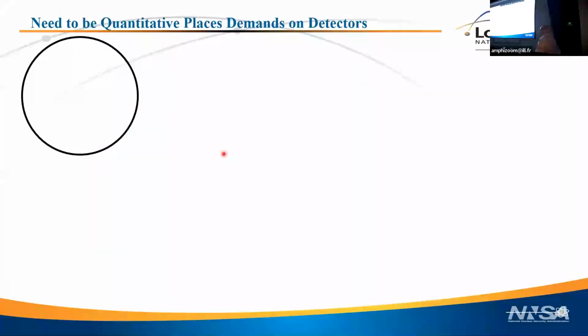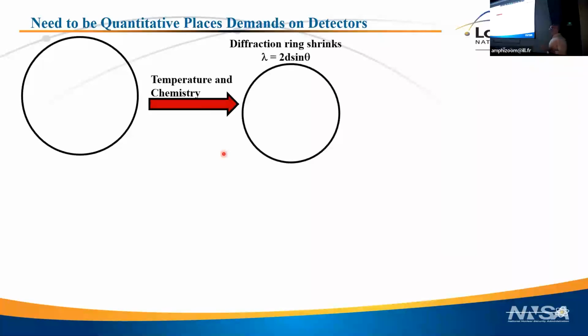So just an example, how do we deconvolute the lattice spacing, for instance, all the microstructural effects on lattice parameter? Well, if we look at just a schematic of a Debye-Scherrer cone, that's supposed to be a circle, right? If we have a stress-free powder or a stress-free sample, then a Debye-Scherrer cone will be a nice circle. If we change temperature, for instance, temperature is a scalar, and maybe I should say this should focus on cubic materials where you have just a single thermal expansion. It's a little more complicated in hexagonals because your thermal expansion is direction dependent. But if you just change the temperature or the chemistry, those are scalar values. They're going to change the radius of your Debye-Scherrer cone, but that's all, okay?